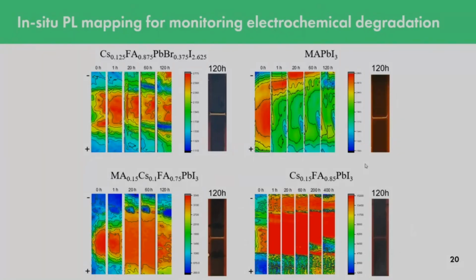Here you can see that during the biasing of the device, during probably the first hour at the beginning of the process, the PL intensity is increasing, which correlates with the information that current is increasing at the beginning. And then we have a depletion of PL intensity, especially along the cathode, the negative electrode. After 120 hours of biasing, it's also visible on simple photos of the devices that the material between the two gold cathodes is completely ruined, unfortunately, except for one, the most stable material, cesium formamidinium lead iodide, which demonstrates much better performance, up to 400 hours, and almost no visible changes on photographs.